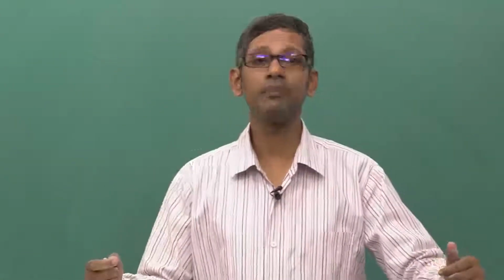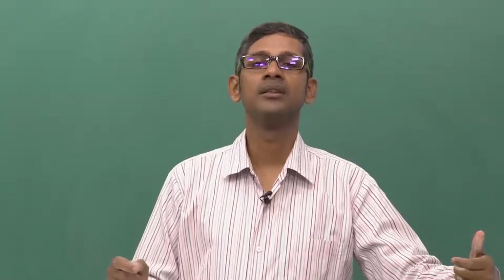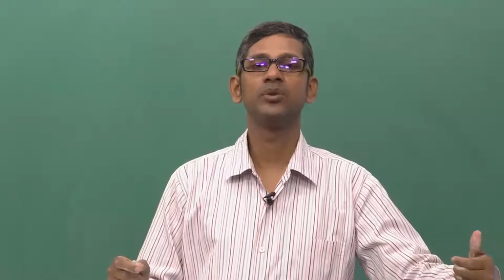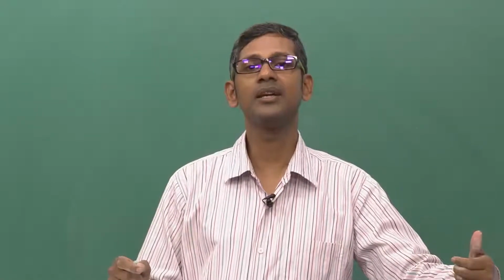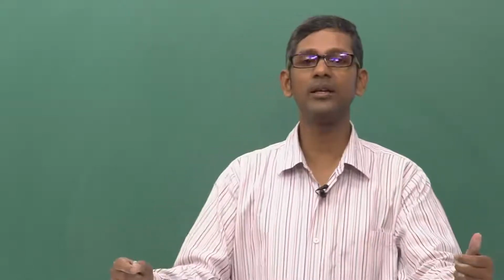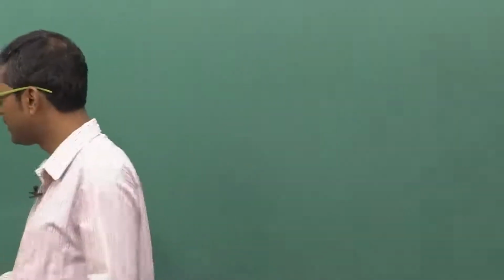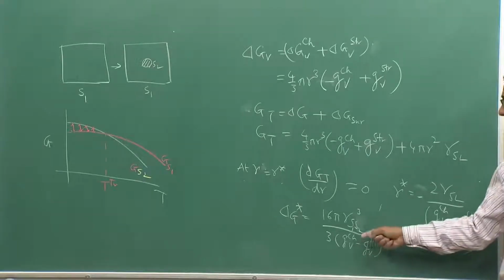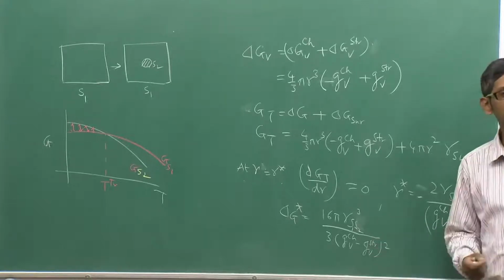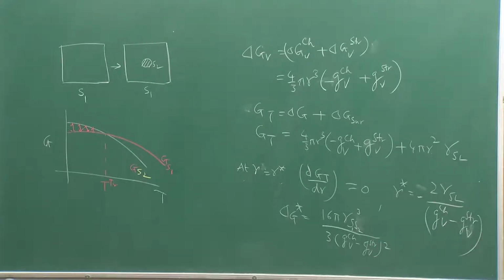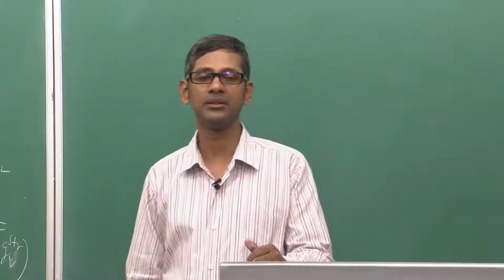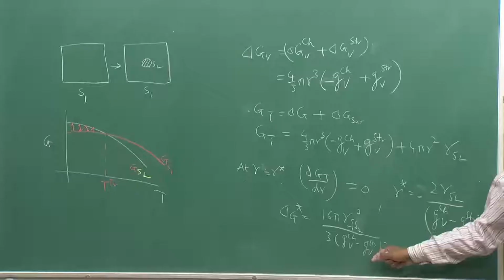Or you can also have a permanent strain because of dislocations. Dislocations can be formed at the interface to create a semi-coherent interface that can lead to permanent strain. Or in case of incoherent interfaces, strain energy is pretty high because there is a lot of distortion of the atomic bonds at the interfaces. So, this value is going to change depending on the type of interface that is developed. As you can clearly see, the nucleation of the phase is strongly dependent on the type of interfaces we have in the solid.